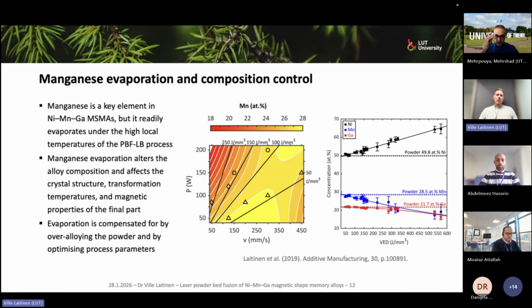Gallium content tends to stay roughly the same. We are losing some of it, but not in a substantial amount that we can actually see a big difference. But nickel tends to pick up what manganese loses. So most of the time with our powders, we just over-alloy them so that we increase the amount of manganese, for example by 2 atomic percent, and then we decrease the nickel content by the same amount. After the optimized process, we actually have an alloy corresponding to a functional material. So we can actually make something that works.